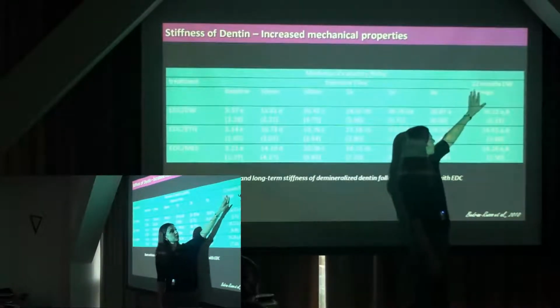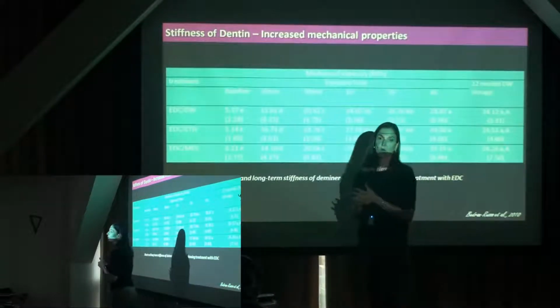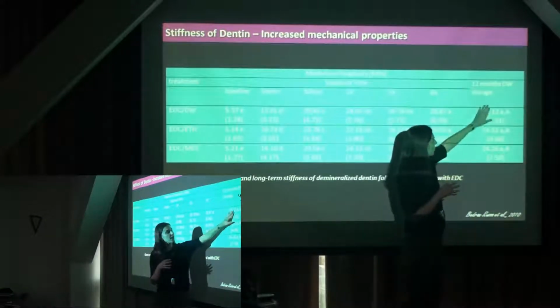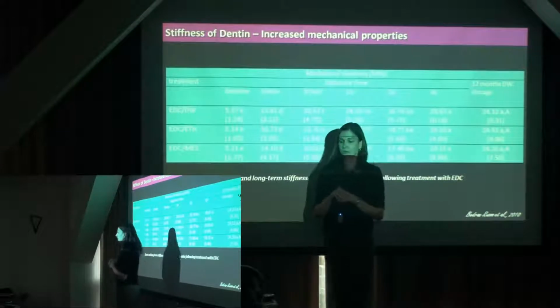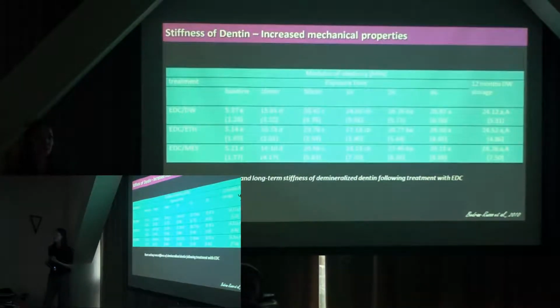nothing happens. This is lower than glutaraldehyde, but what's interesting with all of these is that after we get these beams and we put them in water for a year, and we store them at 37 degrees, and we go ahead and we measure the stiffness again, we saw that there was minimum variation. So that's very important for us because we don't have that ability to remodel and regenerate. So we want materials to stick to it and be stable for a long time.